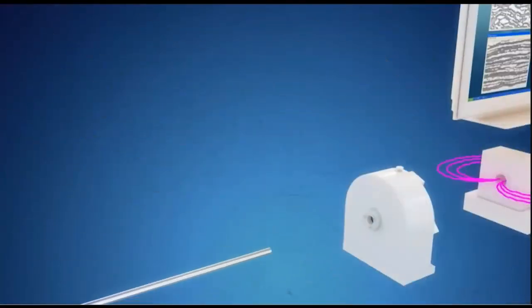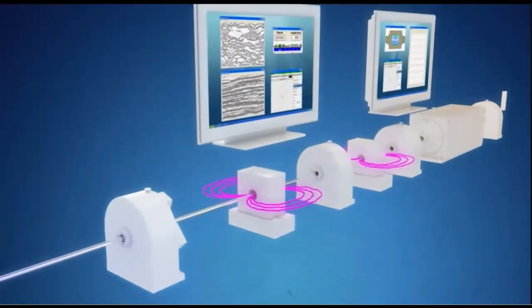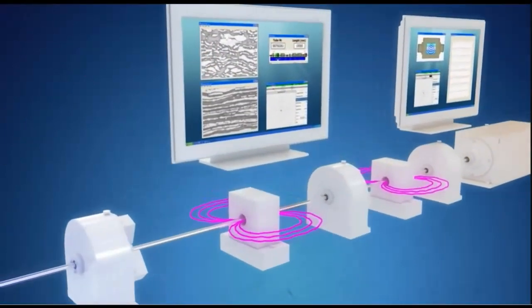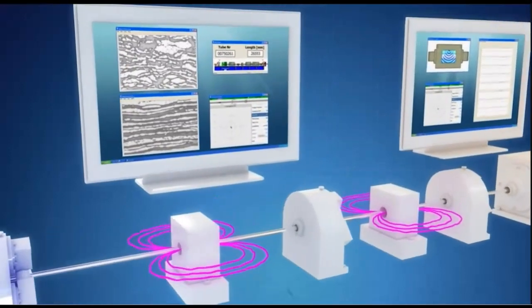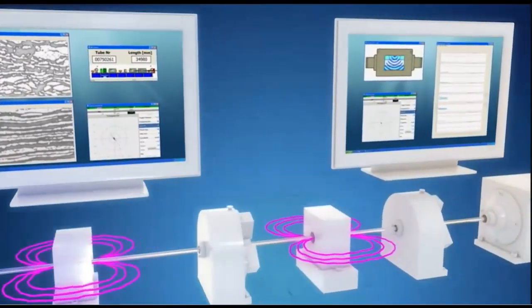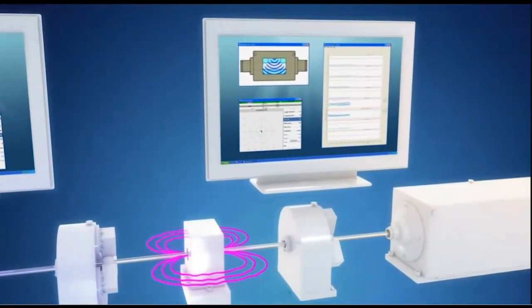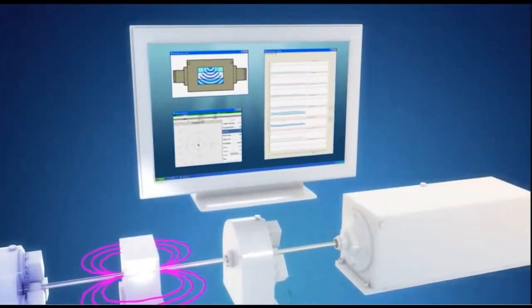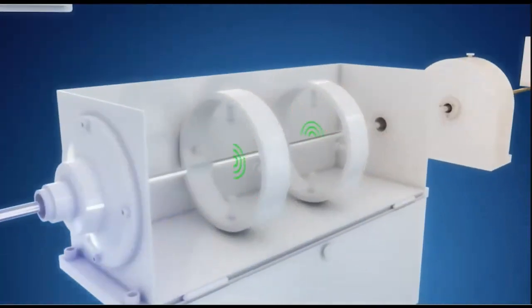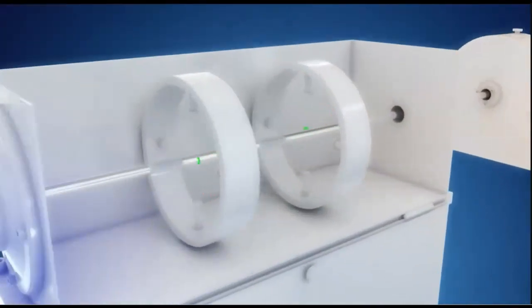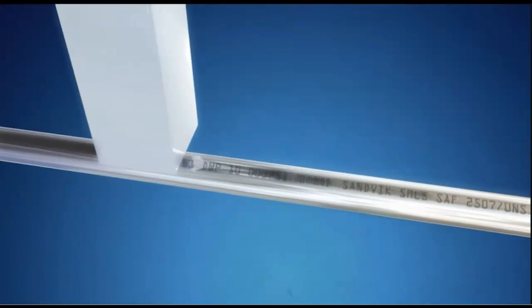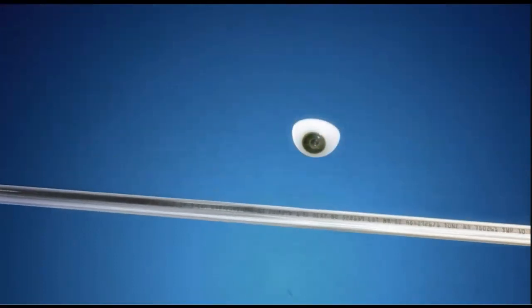According to customers' requirements, the tubes are fully inspected for defects using ultrasonic and eddy current testing methods, set to detect the tiniest defects such as cracks, cavities, or other material defects that the naked eye can't detect. Their dimensions are verified, and they're also checked to ensure they're free of intermetallic phases. This is followed by visual inspection.